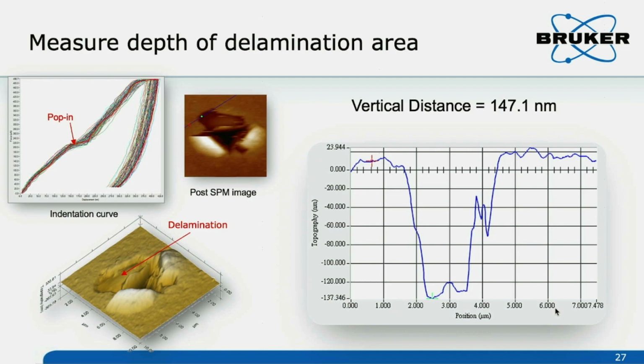We can see there is a step. It's very clear the film just totally delaminated. And the substrate is here. And this is the film. So we can measure the thickness, the step height, by this cross-section. You can see the step height is almost 147 nanometer.